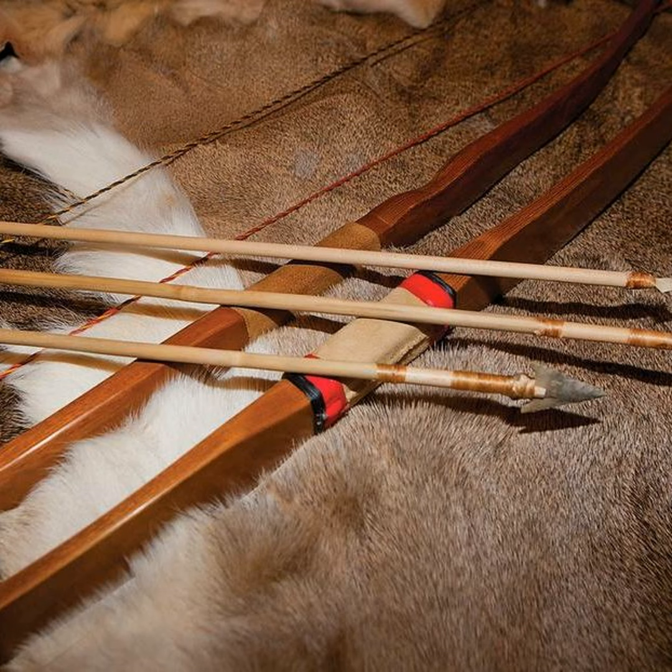The 12 to 18 month period is about dropping the free water and really pulling that moisture content down. But the moisture content is still probably sitting at 40% after a couple of weeks, when a lot of the water is drained out. Over the course of a year, year and a half, you're going to see that moisture content drop down below 30%, probably still be in the 20s, but it could very possibly be in the low 20s, depending on how it's stored, how much air is circulated through wherever these are drying. This is perfectly fine for timber framing.